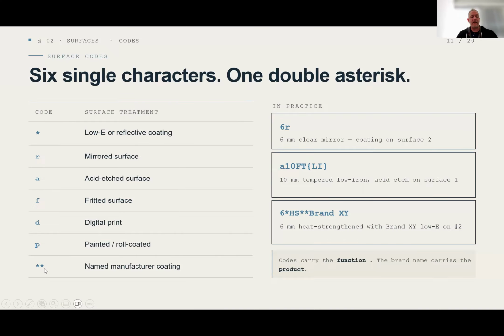And then last, what we have is this double asterisk, and that has to do with if you use a low E reflective coating, how are you specifying that? So when we look at the third example, it's going to be 6 mm heat strengthened, low E on surface 2, and then the whole makeup trails with a double asterisk and then you can specify the coating after the fact. So it knows that the first one listed is, this could say double silver, low E. It could be the specific brand that you're specifying.